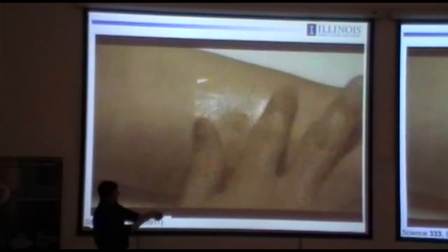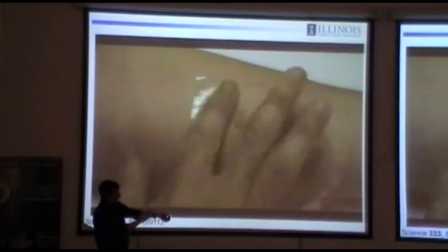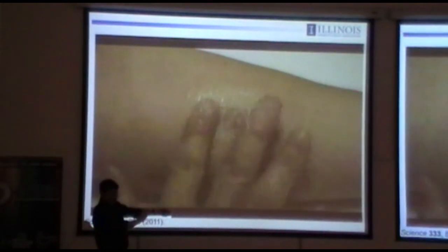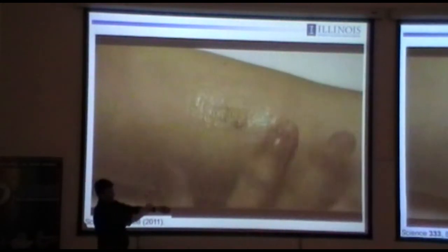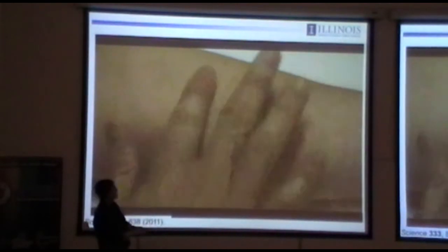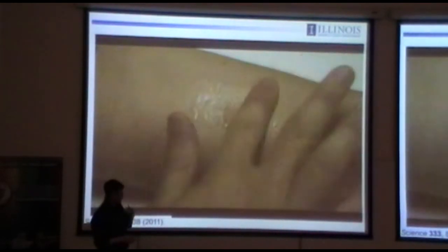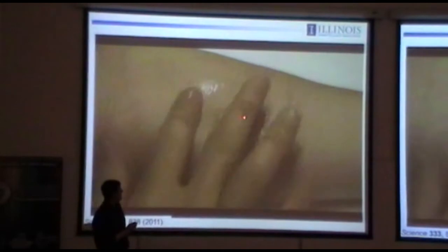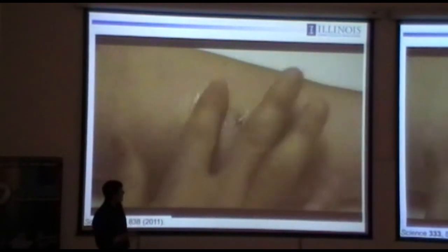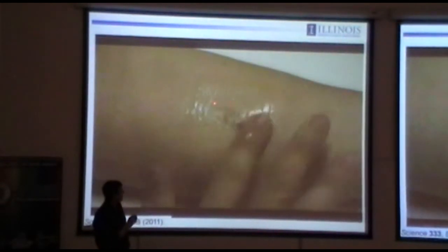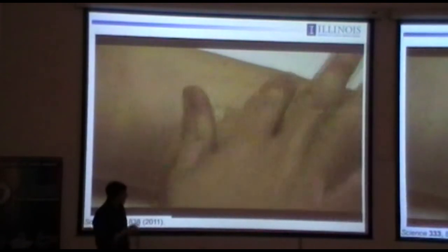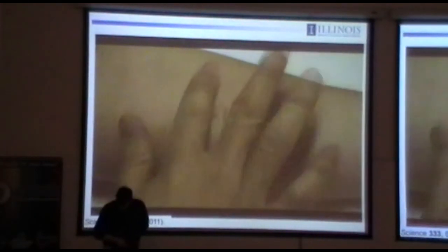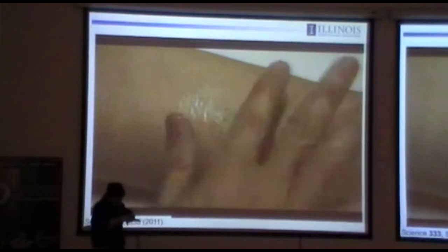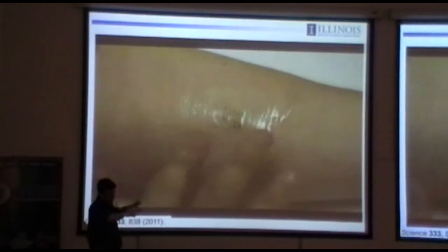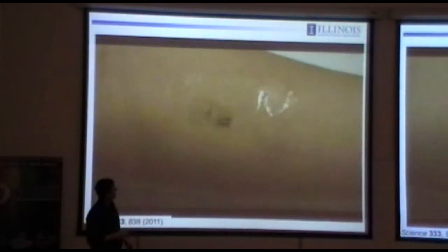What you're seeing is the device is laminated against the skin, so the circuit is in direct contact with the skin. On top of the circuit is that thin silicone substrate, and on top of that is this transparent water-soluble polymer, PVA in this case. And the postdoc has put it on his forearm and is now slowly dissolving away the PVA by applying a little bit of water with his index finger. So the PVA will soon be gone, and at that point, the epidermal electronics will be in conformal contact, even with the structured surface of the skin, and adhering there just by van der Waals interaction.